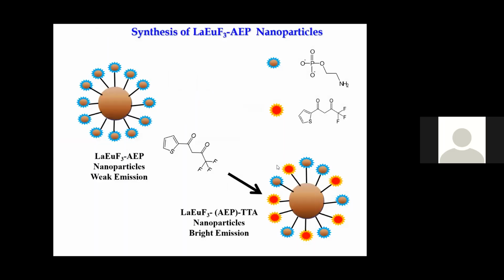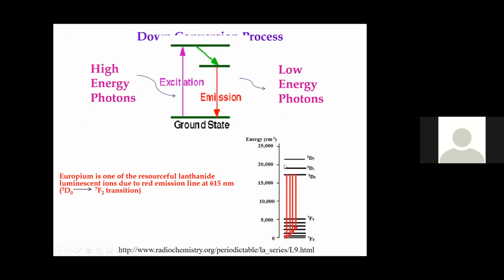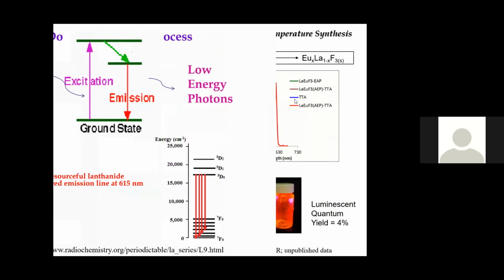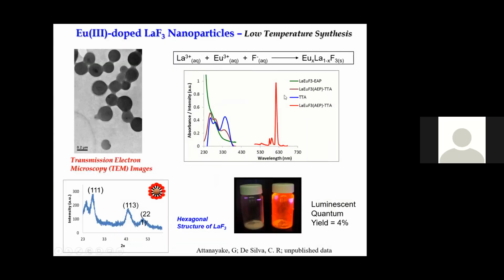So that's the bottom line. All right. So we made this system called lanthanum europium fluoride and coated it with this ligand. And when you shine light, like we said, it gets excited, it gets transferred to the metal, and you get the emission from the metal center. So you can see in this graph, the left side of the graph is absorption, and the red curve on the right side is the emission. You see, yes, it works.